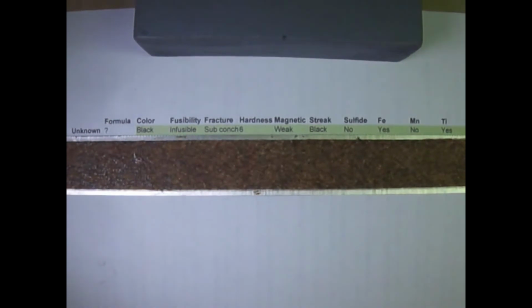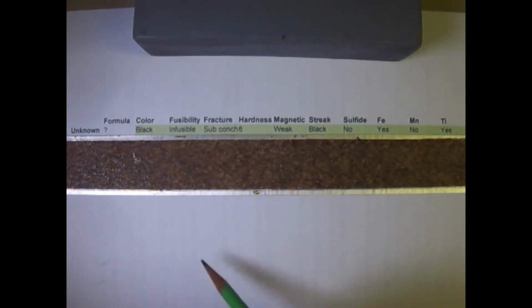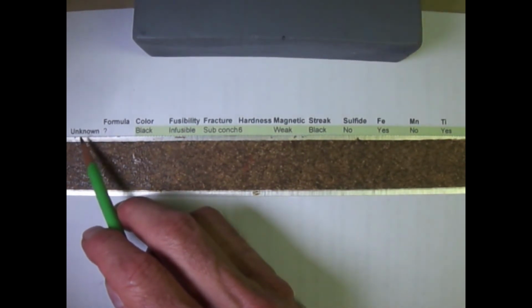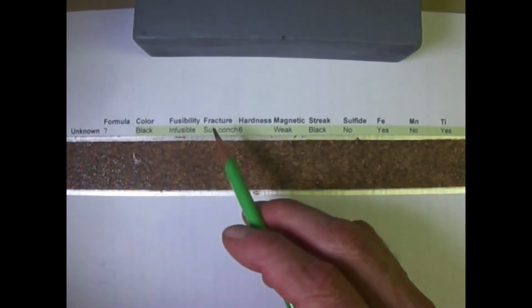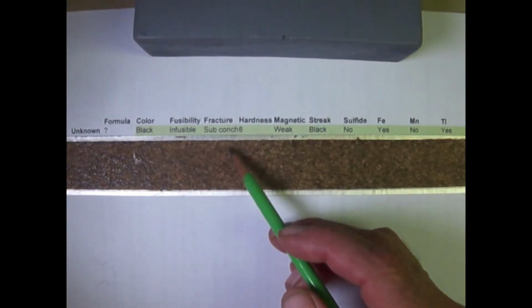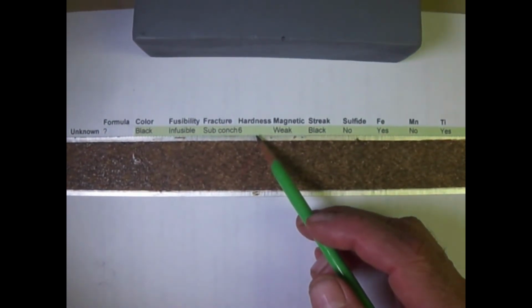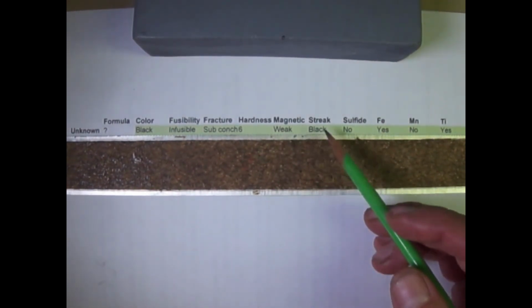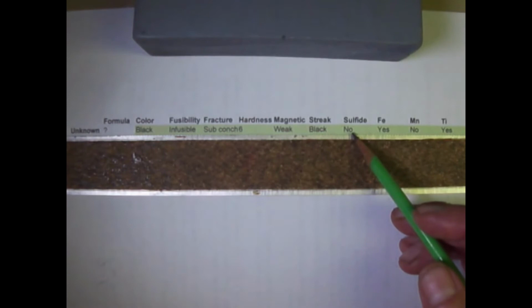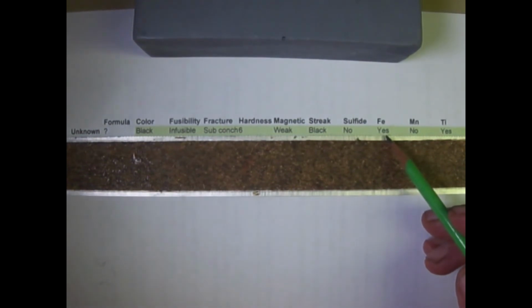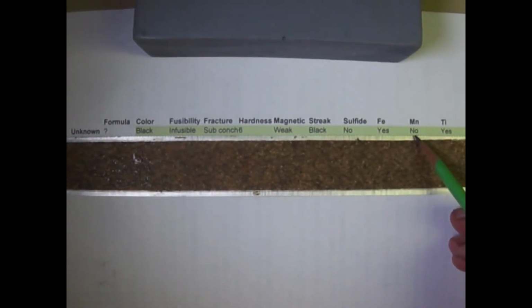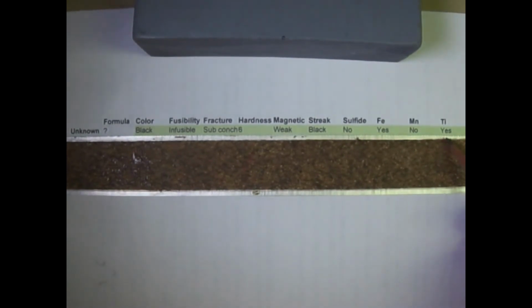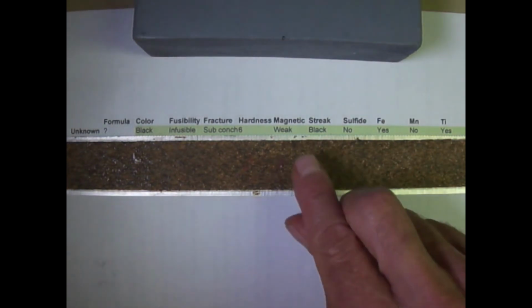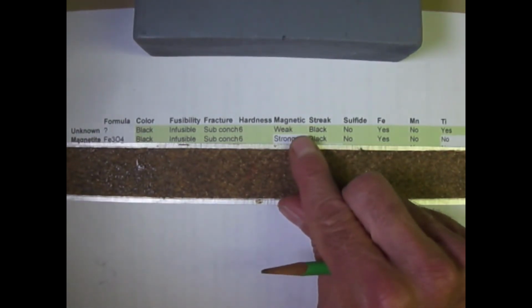All right, we are done. And here's a summary of our results. This first line is the properties of our unknown black coating. It was infusible, the fracture was subconchoidal, the hardness was 6, it was weakly magnetic, it had a black streak, it was not a sulfide as we tested with the lead acetate paper, it did contain a lot of iron, it did not contain manganese, and that last test was for titanium, and it contained a whole bunch of titanium along with the iron.